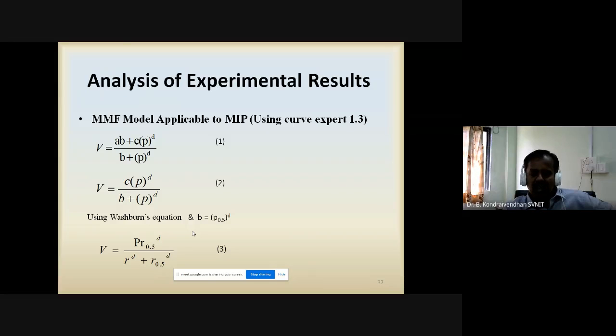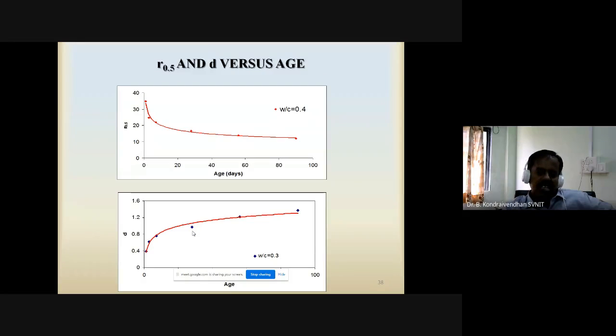Okay, there is not much complication, but the only thing is it's a tedious process, and we have to do the hydration arrestation, all the procedures we have to follow strictly. Okay, then if you plot, this is the experimental data. If you plot R0.5 versus curing age for a typical water cement ratio, this is how it looks. The R0.5 reduces over the age.